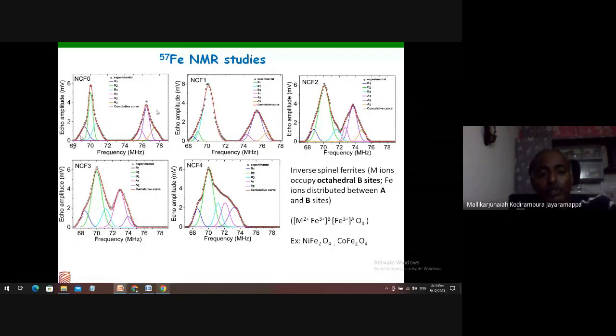This is for the pure system. As you can see, go to the bottommost line. This is a different example. It is not aluminum I am changing here; at the iron site, I am changing the cadmium. When I change the cadmium concentration from 0 to 0.4, I did not see any peak corresponding to the A site. That clearly shows that M ions occupy octahedral B sites and iron ions are distributed between A and B sites. Ultimately, I have replaced all the iron atoms which were located in the A site, or they have shifted to the B site.